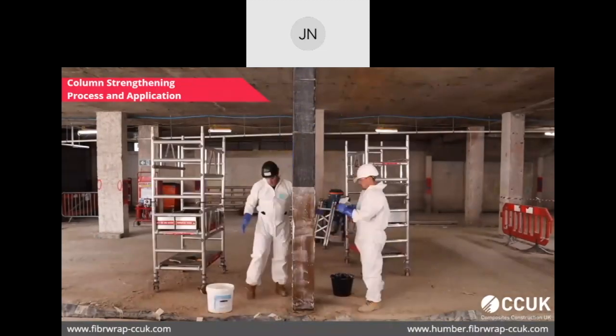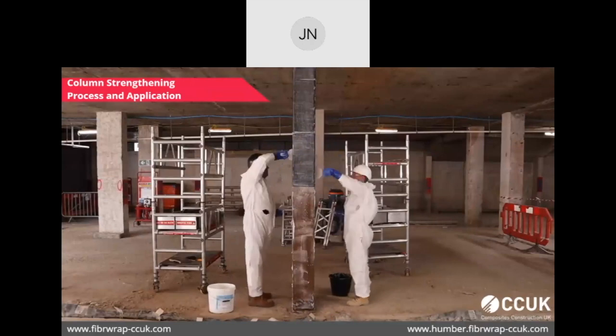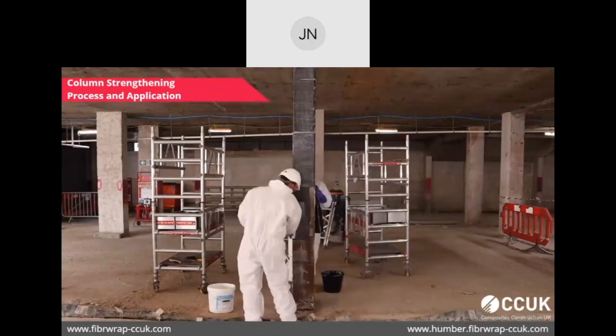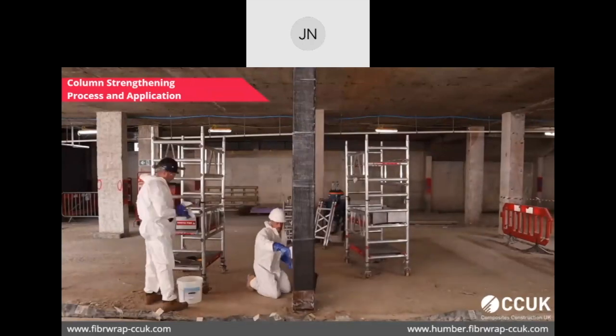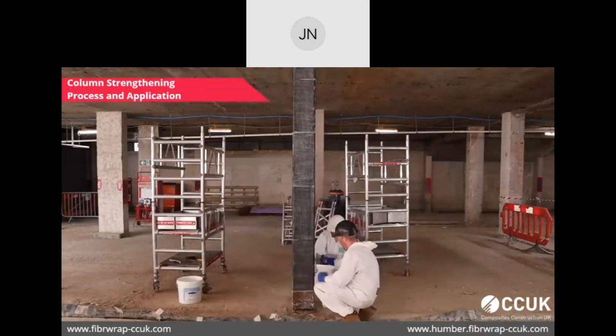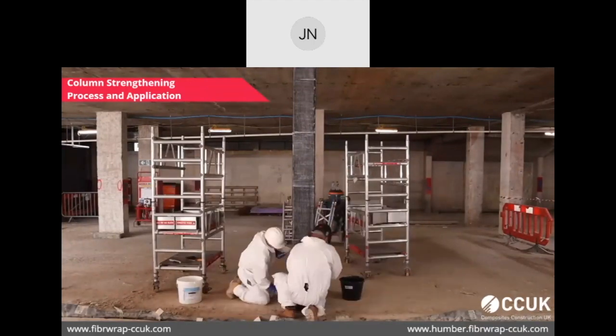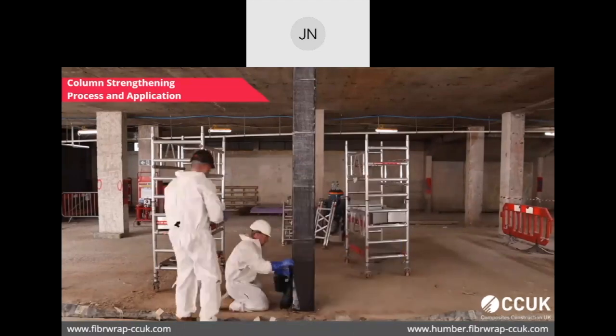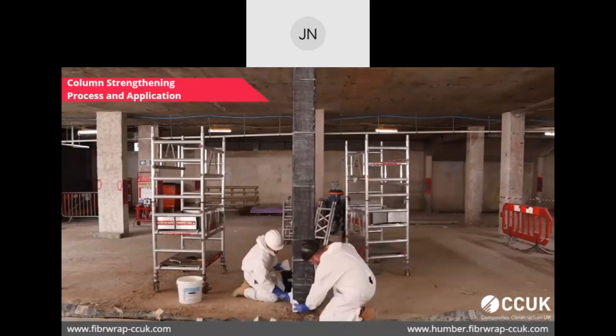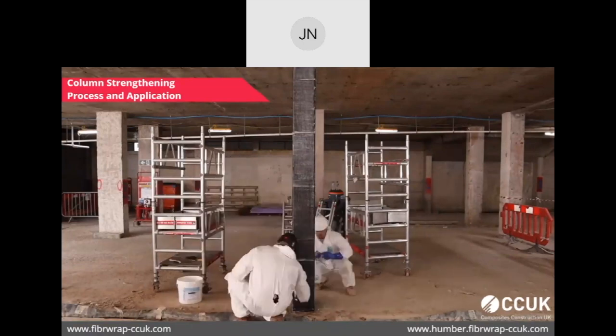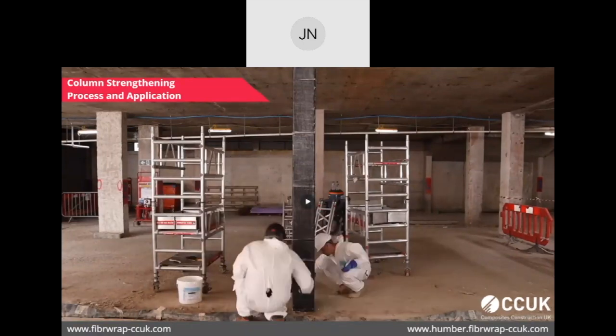Because it's a vertical and overhead application, the maximum layers you can apply in one day is 3. Because after 3, the saturated weight of fiber is too high and it might slide down or fall off. That's why you have to wait for it to initially set before you apply further layers if there is an application of more than 3 layers. So in vertical and overhead application, you're limited to 3 layers per day. So once that is done, then you can leave the column exposed like this, so it will be black in color, or you can put plaster, paint or render over it, or you can put a fire protection coating on top of it if it is required.